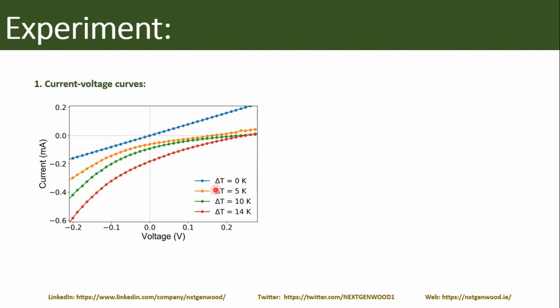When we start applying some temperature difference, we see that there is some change. First of all, the curves become non-linear. This is quite easy to explain, because when we have one side of the membrane at a higher temperature than the other, the electric double layer width also changes, and the nanochannel becomes asymmetrically charged. So the whole curve becomes more diode-like because of that. We can also see that the whole curve is shifting, so we do not cross at 0, 0 anymore. There is some potential here, which changes when we increase the voltage.